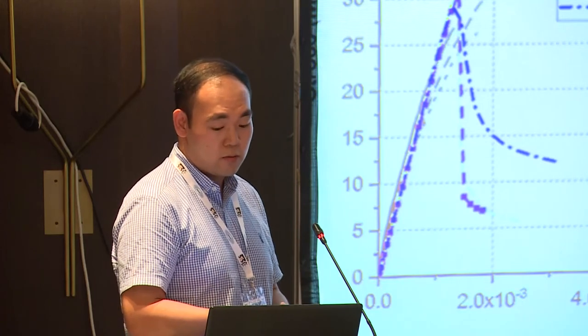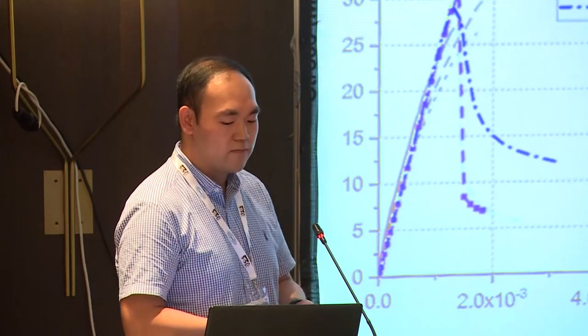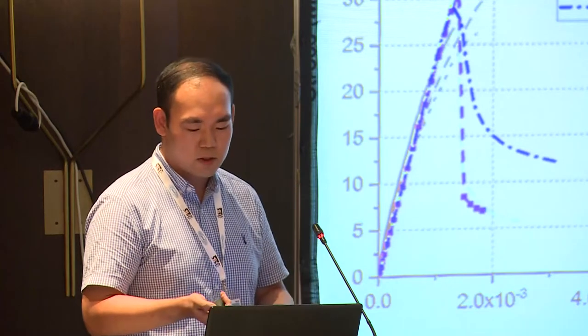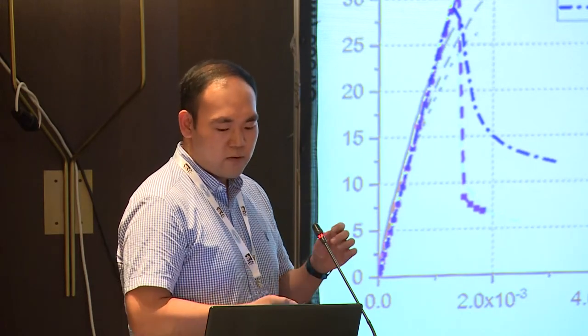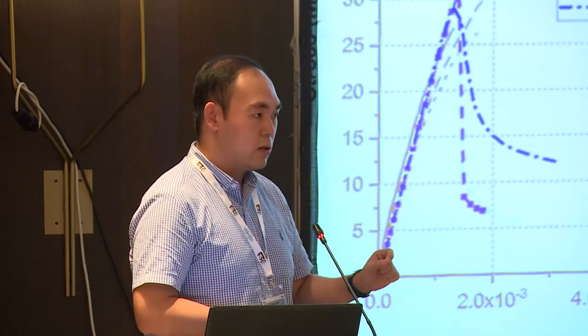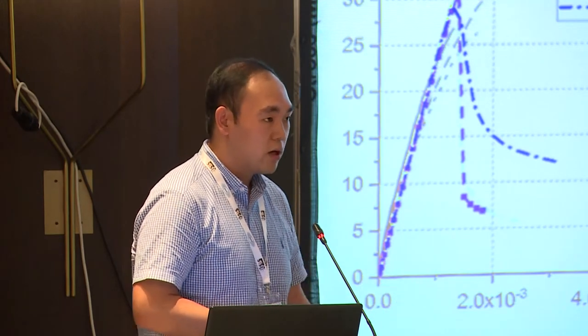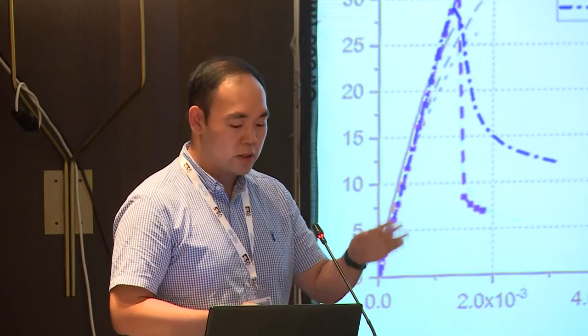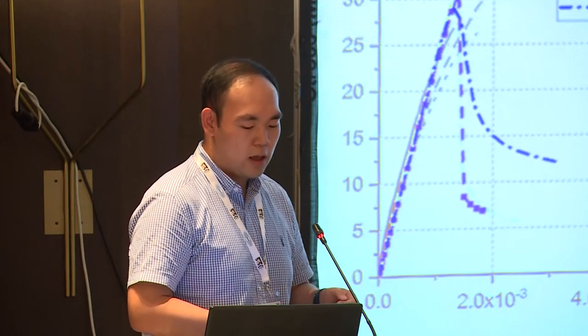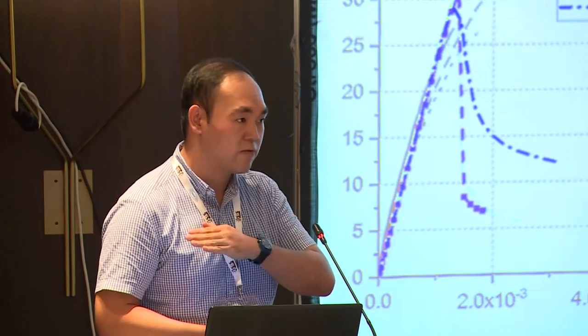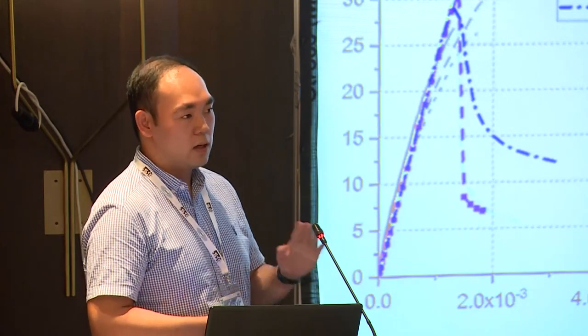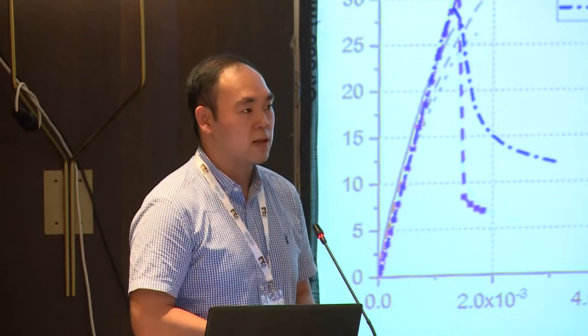So actually, some of the work is still going on for the cohesive parameter models. I just showed some of them that are completed. It depends: if your ITZ is not strong enough, it may not reach the peak. And if it is too strong, you may get a very slowly dropping softening. So you have to try and calibrate that.